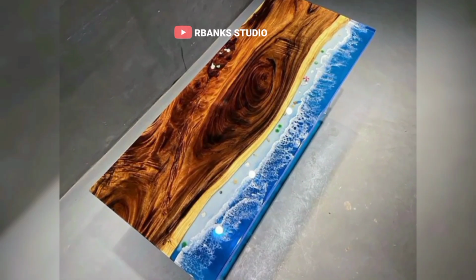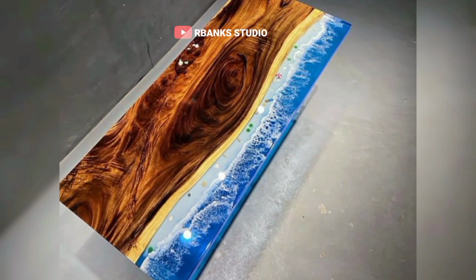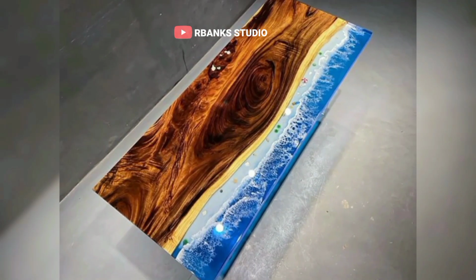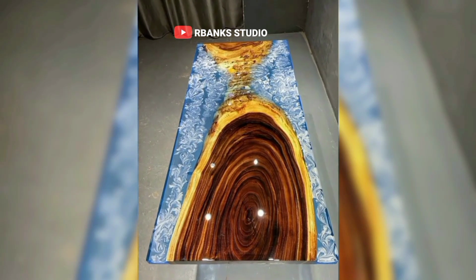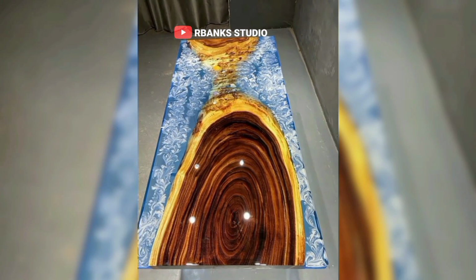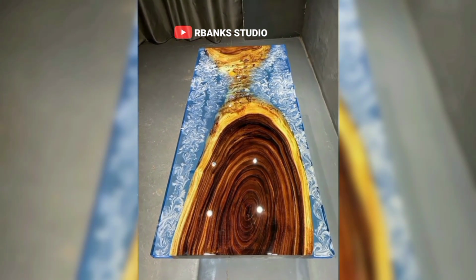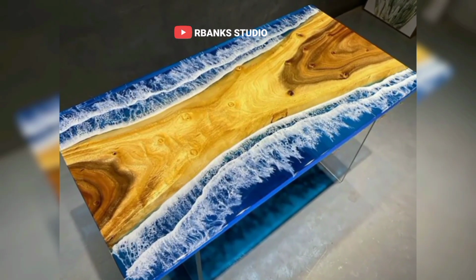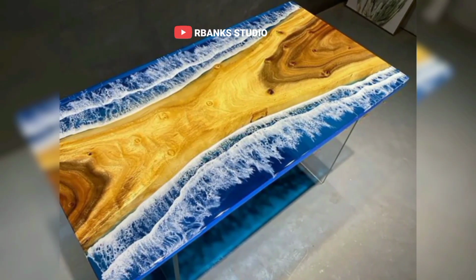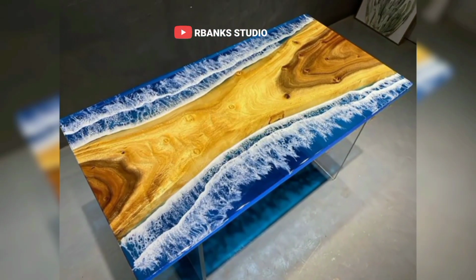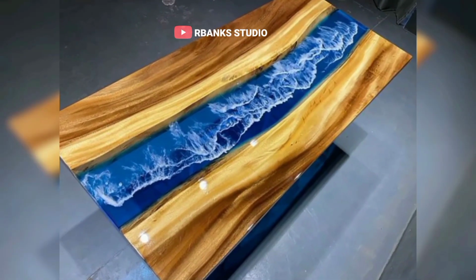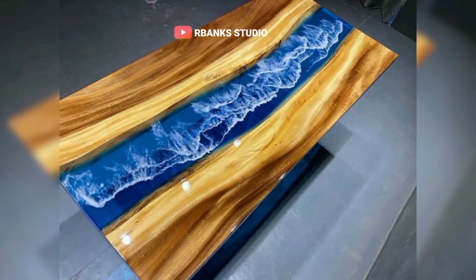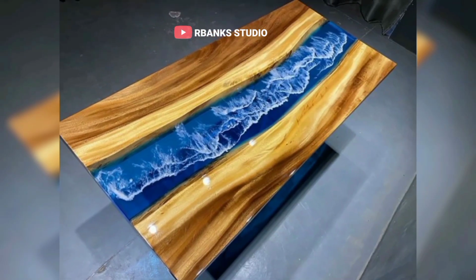Sanding the wood surface before applying epoxy is critical. A smooth, even surface helps the epoxy adhere better and reduces the risk of air bubbles, which can weaken the finish. I also make sure the wood is completely dry and free of dust or debris. Any contaminant can affect the clarity and strength of the epoxy layer.